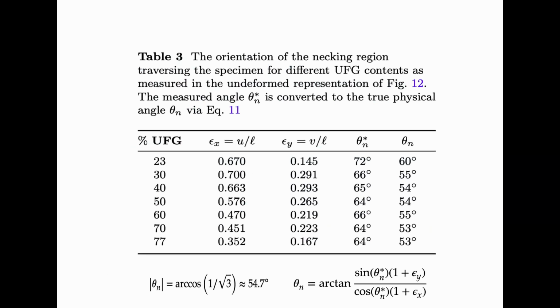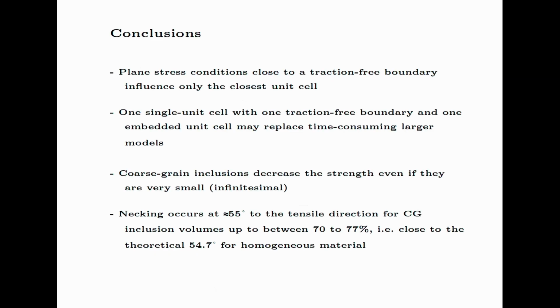And then this is a table showing the angle towards the tensile direction. And this is on the deformed specimen, and this is on the not deformed. And you see it's between 53 to 60 degrees. So if you don't have the one with the thinnest skeleton, that one sticks out. But otherwise, it's exactly like what you get if you have a homogeneous material plate and you put it under tension, and the angle is 54.7 degrees. So it's like nothing happens because of that. So plane stress condition close to the traction-free surface boundary.